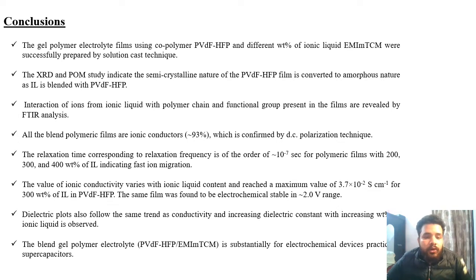The relaxation time corresponding to the relaxation frequency is of the order of 10 to the power minus 7 second for the polymeric films with 200%, 300%, and 400% of ionic liquid, which indicates that fast ion migration is happening inside these films. The value of ionic conductivity varies with ionic liquid content, and reached a maximum value of 3.7 into 10 to the power minus 2 Siemens centimeter inverse for 300 weight percent of ionic liquid in PVDF-HFP. The same film was found to be electrochemically stable in the 2 volt range. The dielectric plots also follow the same trend as the conductivity, and an increasing dielectric constant with increasing ionic liquid is observed. The blend gel polymer electrolyte is suitable for electrochemical devices, and practically for supercapacitors.